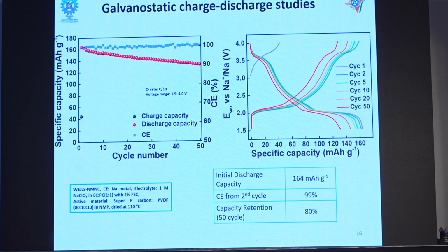Then, since it's a new material, we subjected it to galvanostatic charge discharge studies. Galvanostatic means current is constant. So we keep the current constant and we apply a potential window, and in that potential window your battery is cycling. So when we did the galvanostatic charge discharge studies, note that the voltage here is 4 volt. So we are playing around a little bit with the voltage in this particular work, and we want to figure out how the voltage window is affecting your electrochemical mechanism.